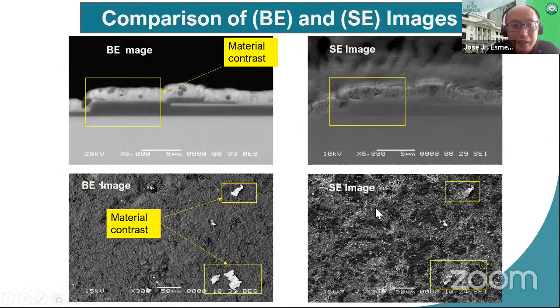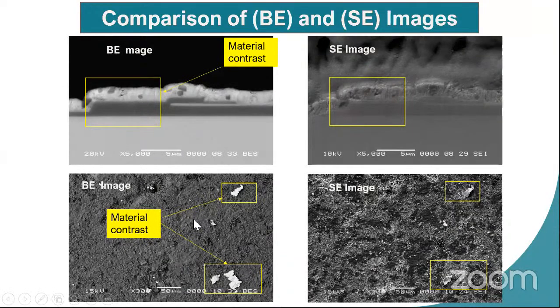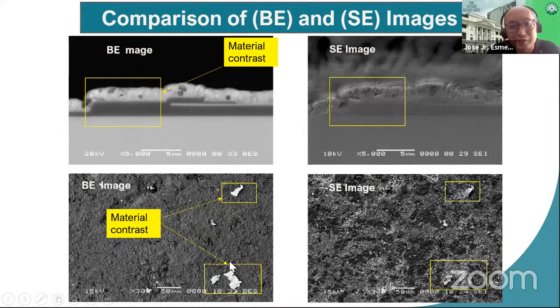Similarly, in the image below, we can see from the secondary image there's a lot of scratches, and you can see the features differently. And then in the backscatter image, we can see the material contrast. You can see from here that this is lighter, it means it has a higher atomic number, so there is more reflectance. And here, this is darker, there's more transmission, so this is a lower atomic number. So that's the difference between the two. This one is for analyzing the surface, and this one is for analyzing material differences.